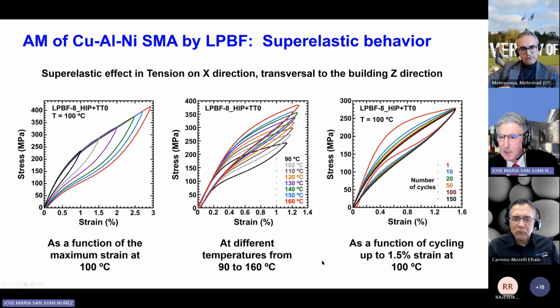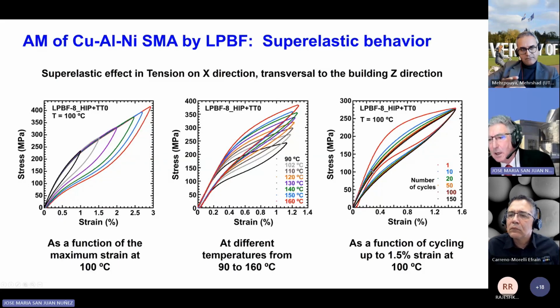What is interesting also is that we have done a cycling of up to 1.5 strain, and after some 20-50 cycles of training, we get a completely reproducible superelastic cycle up to 1.5 strain, and all this is at 100 degrees centigrade. So this is a very interesting aspect for an additive manufacturing produced sample, because this means that this could have the performance required, for instance, for many actuators in space.